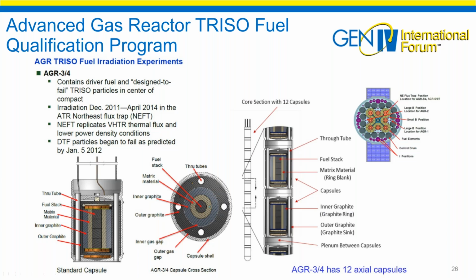AGR-3/4, again, was the fission product transport test. Now, what was unique to this is we had to make design-to-fail particles. We had to make fuel that had thin layers, missing buffers or small buffers, and we carefully took 20 of these particles where we intentionally didn't make them right and put them in the very center of the compact.